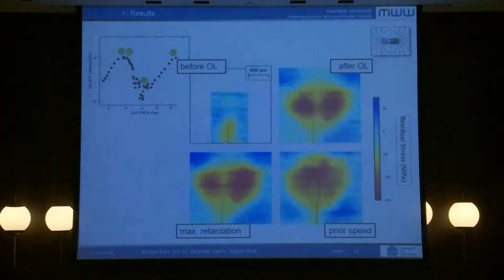And then you can also investigate the crack growing through the plastic zone. So this is before the overload, after the overload at position 2, here at position 3, where you have the maximum retardation, the slowest crack propagation rate. The crack tip is still inside the compressive zone, and here at the prior speed, now the crack is still somewhere inside the compressive zone, but the crack also increased, and therefore here you would expect typically for this delta K a crack propagation rate up to here, so you still have an influence even if you are here now at the same speed as you have been here before, but with an increased crack length and therefore an increased applied delta K at least.